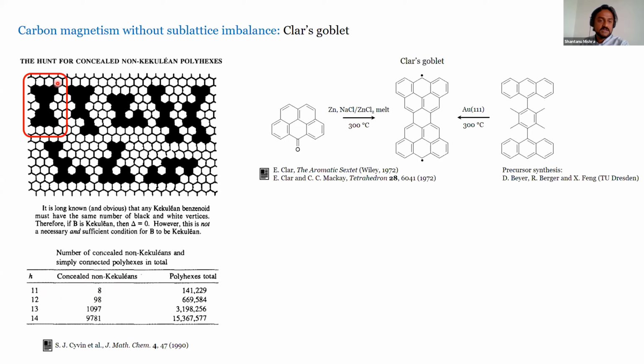Now, the simplest of these, which is this mirror symmetric structure, is called Clar's goblet, which was already envisaged by Clar in 1972, and he tried to synthesize it through this ketone-based precursor, and it did not work. What we tried to do is to replace this precursor with something that might be amenable to on-surface synthesis. So a 6-fold substituted benzene ring with 2 anthracene groups and 4 methyl groups. And if you replace the Clar's catalyst with a gold 111 surface, it turns out we indeed can synthesize it.